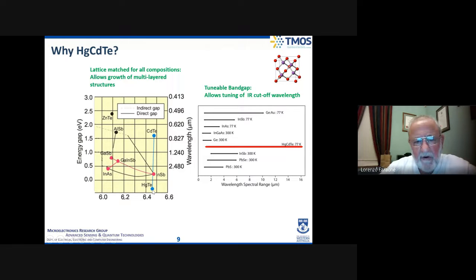The important thing, which I've already noted, is that mercury cadmium telluride, this blue line, from mercury telluride to cadmium telluride, lets me change the energy band gap from just over 1.5 electron volts all the way down to a semi-metal, which has a negative band gap. That means I can span the shortwave infrared, the midwave infrared, and the longwave infrared, which all sit around here somewhere, with a single material system, just by changing the ratio of mercury to cadmium in the alloy.